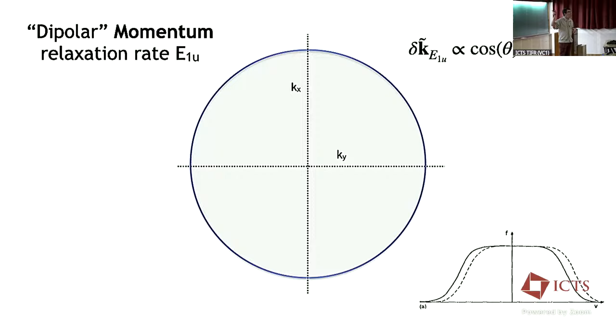The only processes which allow that state to relax are processes which take momentum from the electron system. So this is an important point, and it'll have a particular relaxation time that we could associate with it. It's the rate of momentum relaxation of the electron distribution. We could also call it, and that's the language we use in our papers, the E1U relaxation time, because it looks like this p-wave deformation, if you will, of the Fermi surface.